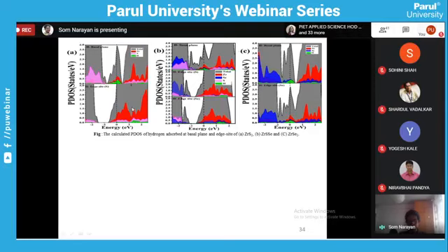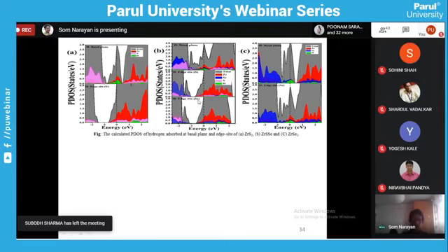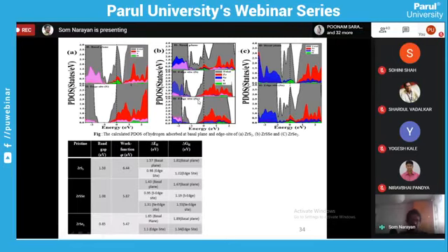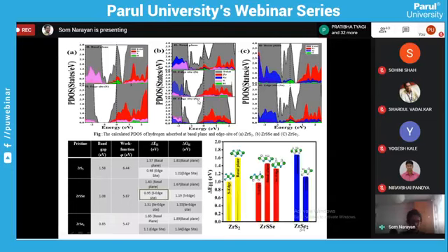So it shows that the interaction between ZrSe2 and hydrogen is lesser as compared to ZrS2 and ZrSSe. We confirmed this with their adsorption energy also, and we found that there are two edges. So the S side is more active towards hydrogen as compared to the Se side, and overall, out of the three systems, Janus is showing better results as compared to their parents.